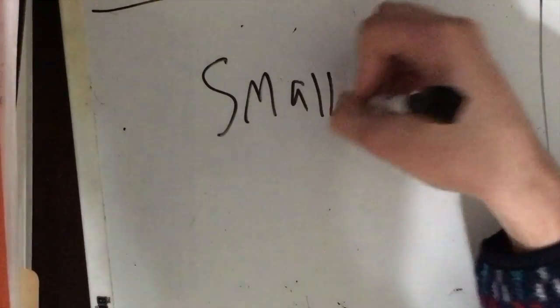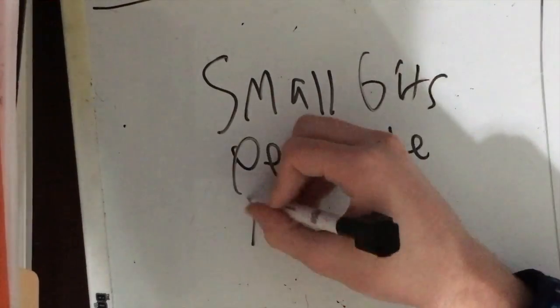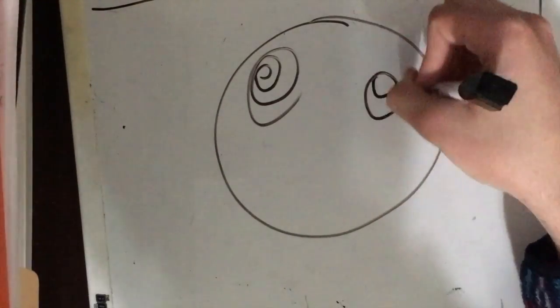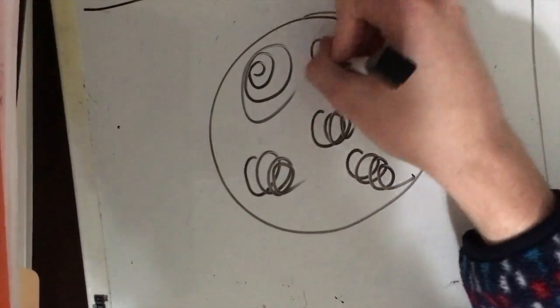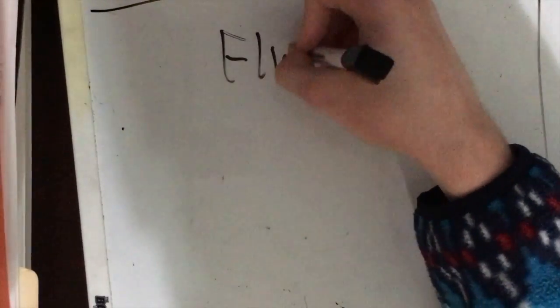Now, let's talk about the Meissner effect. The Meissner effect is when a material transitions to the superconducting state and all magnetic fields are excluded from its interior. Type 2 superconductors are a different story. The magnetic field in a type 2 superconductor is not completely excluded. Rather, it is constrained in filaments within the material. The filaments are surrounded by a supercurrent while in its normal state, leading to a vortex state. A vortex state for type 2 superconductors allows magnetic field penetration. This is what causes the quantum locking of the superconductor.